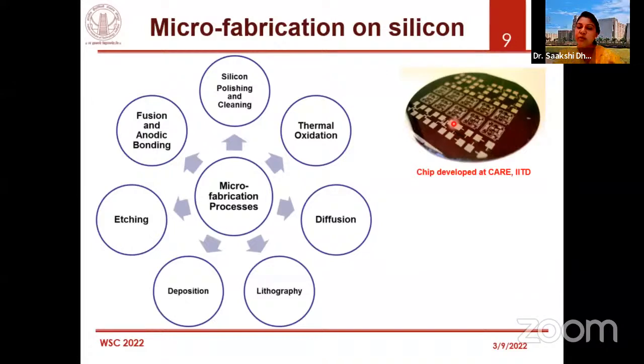So that's how we included test structures on the same wafer so that we are able to see the exact, say, diffusion depth that has happened on the wafer while the transistor was being fabricated. So the ones on the sides that you see are much bigger pads. These are the contact pads made in aluminum. And the ones that are inside are smaller. But these are still not nanostructures. This is still the microfabrication that was done. Later on, we can use these sensors, these transistors as sensors.